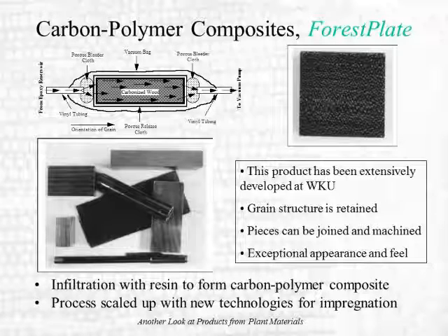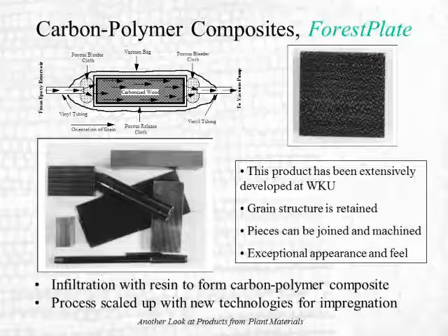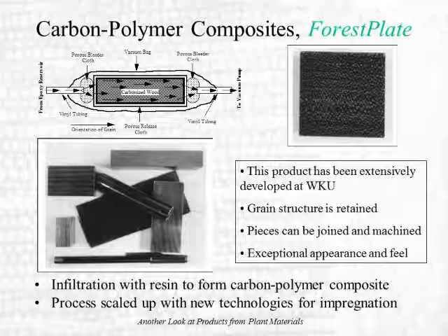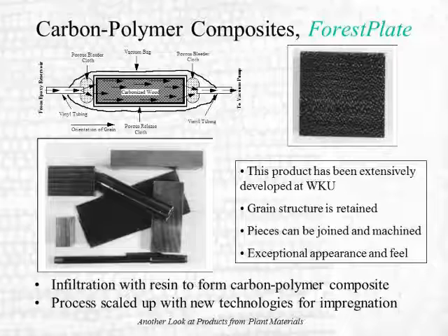It's there as a consequence of the degradation of the wood, and it has that anatomical structure that nature provided it. So it has all the grain structure of the precursor wood. You can convert it into this carbon polymer by vacuum bag techniques or by resin transfer molding or by a variety of other processes that are scalable to large size. And you essentially just infuse the wood pores with resin.